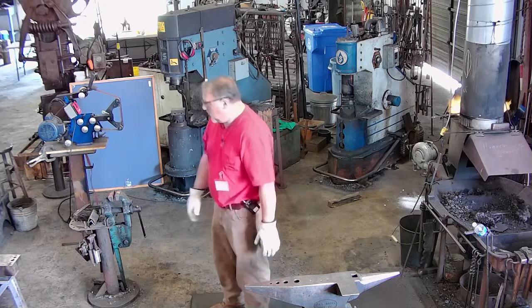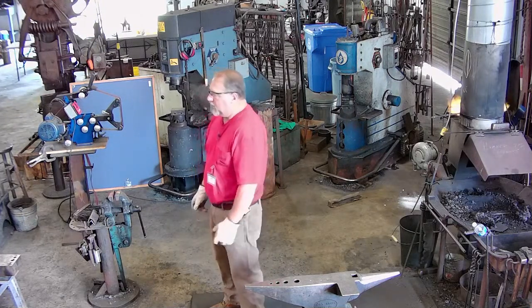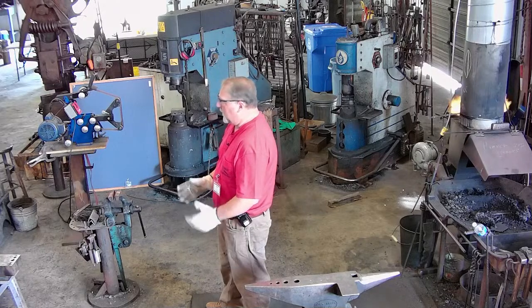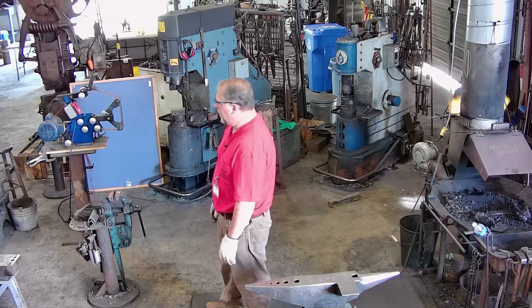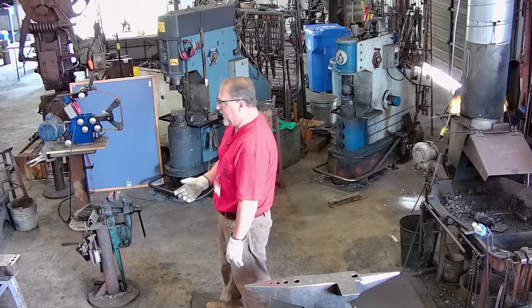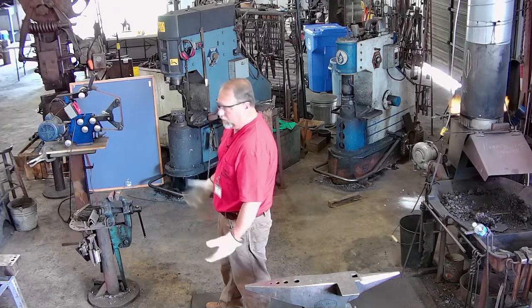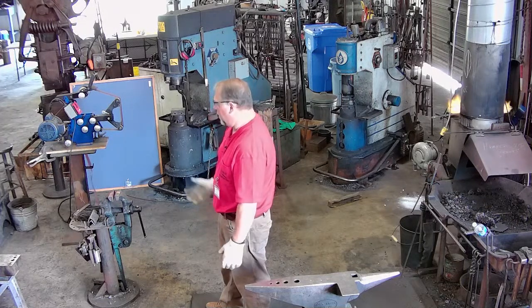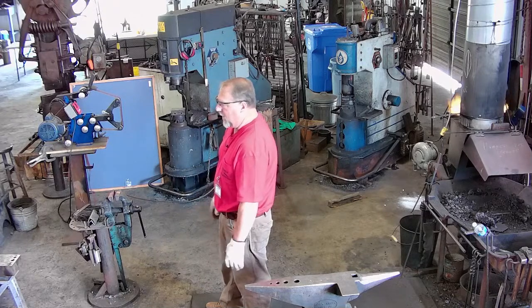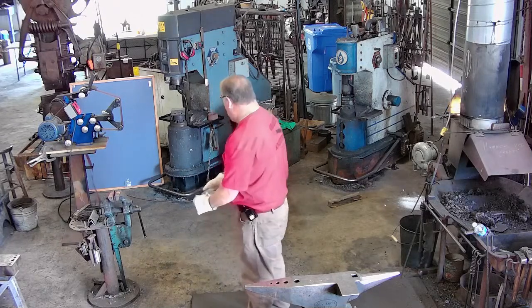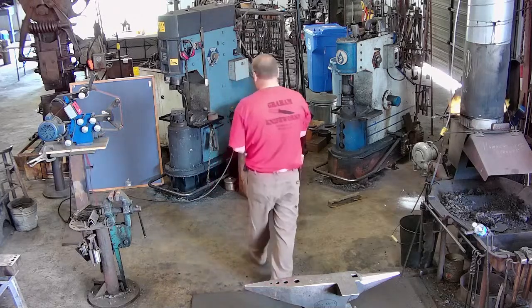So Gary, what kind of flux are you using? I start out my initial weld by soaking my billet in kerosene, and then after the first heat, I'll flux it with borax, or 20 Mule Team borax you get from Walmart or maybe even the dollar store. I forgot to put my flux on, so I'm going to add it this time. Let it heat a little bit.